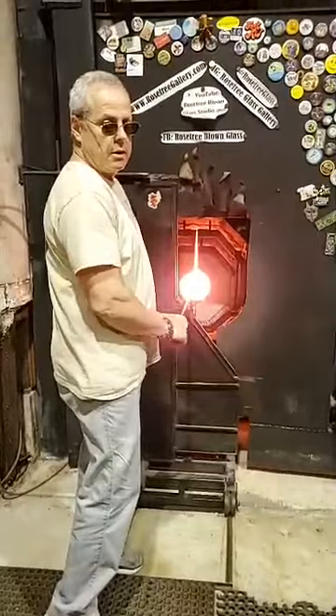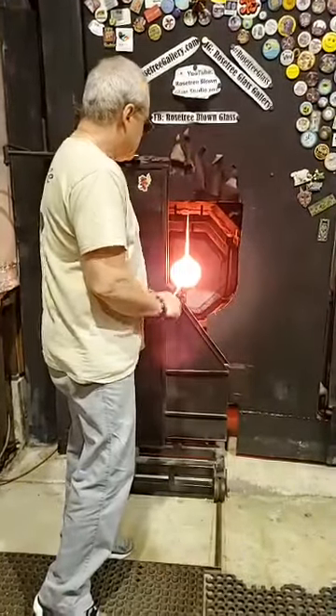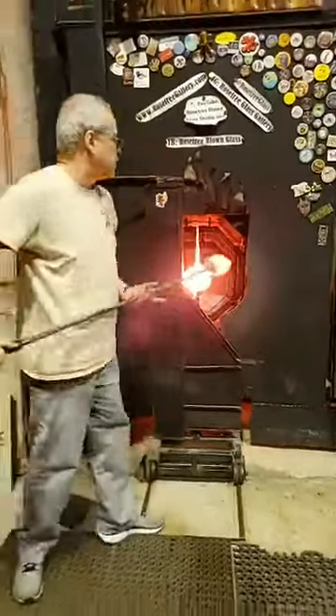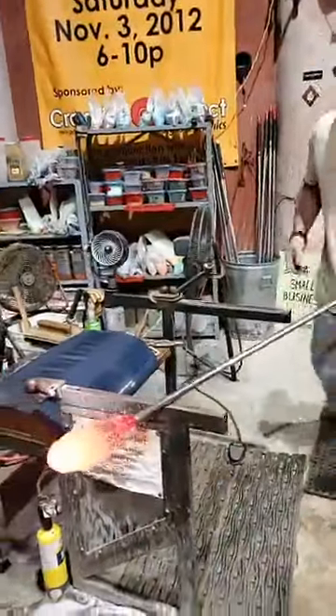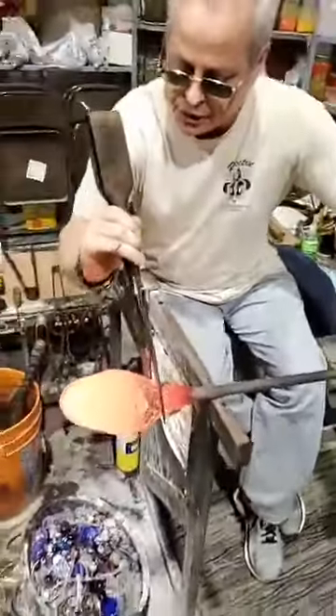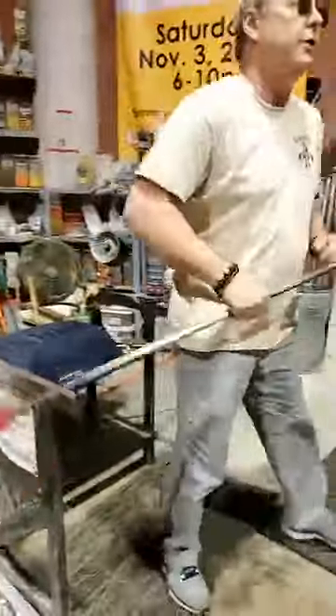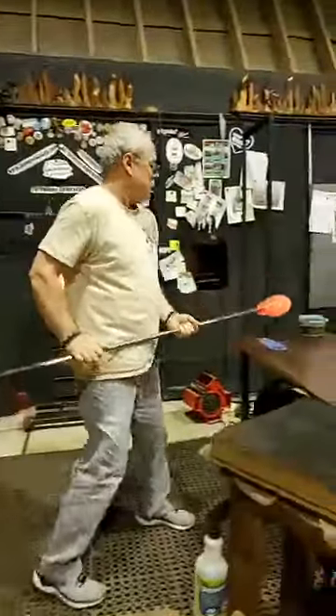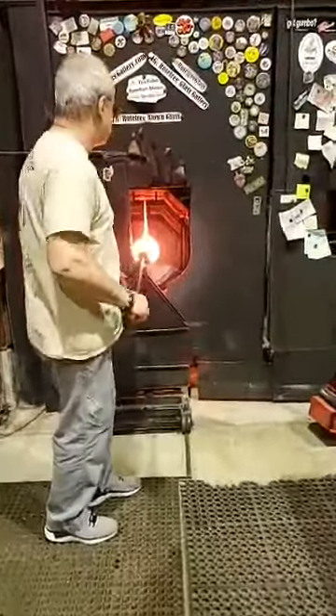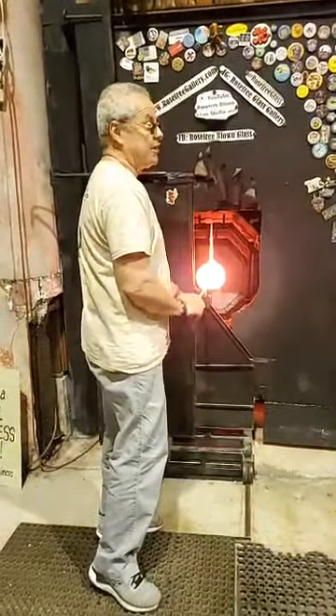So Barry asked Jimmy, how much glass do you need? Right. Christy said, can we see it in its raw state someday? Sure. You can stick around for a second afterwards, and I'll show you. It's not really raw. What we put in is called cullet, and it's actually glass that's melted once. We do that because it's just easier to melt. So it's not as much power for us to melt what's called batch. Batch takes more power to melt because you have to melt it at a higher temperature. So the cullet is about 200 degrees cooler to melt, which doesn't seem like a lot when you're over 2000, but it really is. Jimmy said he needed kilos. Now you're talking different.